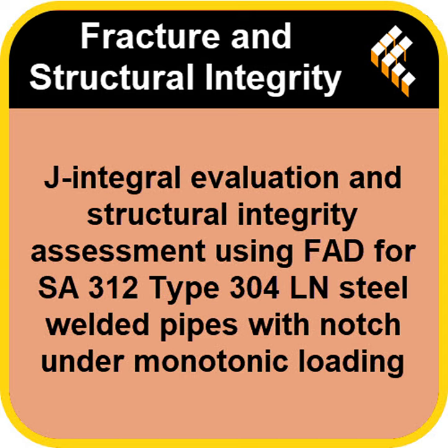a standard lab test. It represents the point where the crack starts to grow stably. Okay, a single value from a test. Pretty much. The J integral via the load-CMOD method, however, is derived from the actual test on the pipe specimen itself. It explicitly accounts for the large plastic deformation that occurs around the crack tip as the pipe is loaded. CMOD stands for crack mouth opening displacement, which they measure during the test.